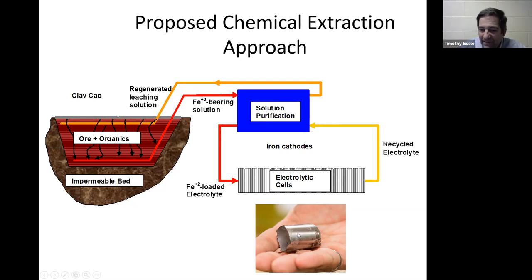And if it's done carefully, this electrolytic iron can be extremely pure, like 99.9% pure iron, which is something you don't get from a blast furnace, because blast furnaces tend to put a lot of impurities into the iron, sulfur, carbon, manganese, and the like. So this would be metal that would not need to be further refined. You could use it straight up for alloying.